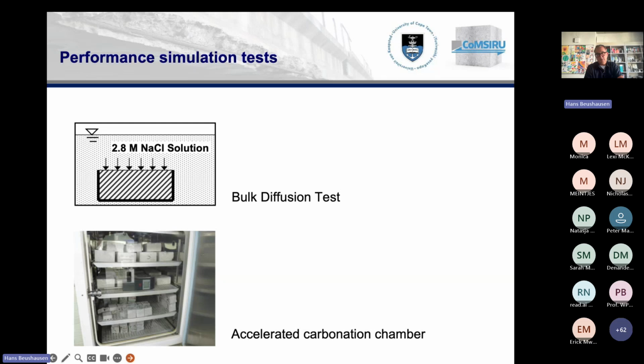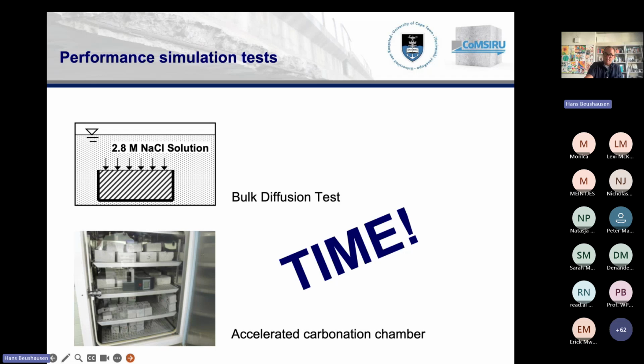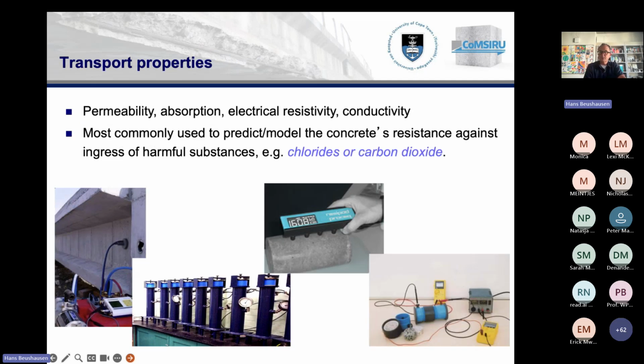And quite similar, in the carbonation chamber, we have an increased carbon dioxide concentration, and we measure how fast the concrete carbonates over time. And these are great methods because they give us a direct handle on the resistance of the concrete against these mechanisms. The problem is that they take a lot of time. So we can use them in research, but we can't use them for mix design and quality control because these tests take about 3 to 4 months, and we can't wait that long before we know whether things worked well on site or not. So here we look at transport properties, and this is also what we use in South Africa for our approach. And here we talk about permeability, sorptivity, resistivity, conductivity, and these things.